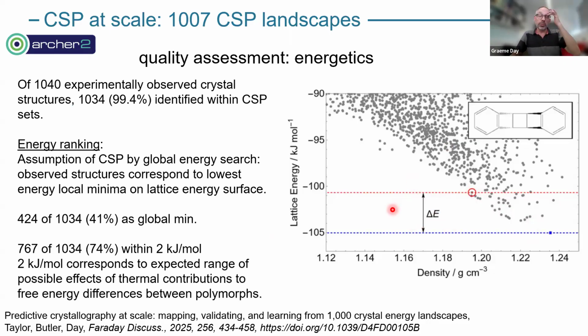Okay, so in terms of stats from this, 1,007 molecules. Some of these were polymorphic, so there were actually 1,040 experimentally observed crystal structures that we were targeting. Most of those got found. Over 99% of those were found by the CSP process. There were a few that we now understand that didn't get hit by the CSP, and so that's allowing us to then improve our workflow for how we're doing CSP for newer molecules, but largely that's very good success.